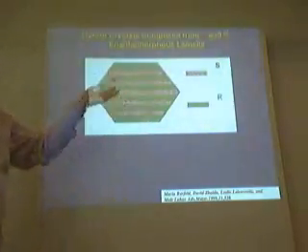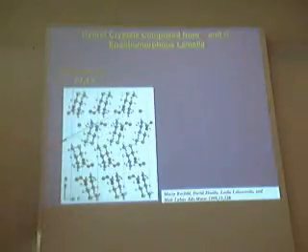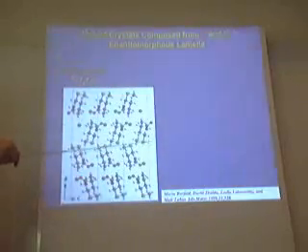And therefore we thought these are actually lamellar twins. They are micron large, and therefore they diffract independently. But you cannot use it for separation of enantiomers, at least by seeding. And the reason for that, we shall see immediately, is that these molecules have strong interactions between the hydrophilic groups, but very weak interactions between the hydrophobic groups.